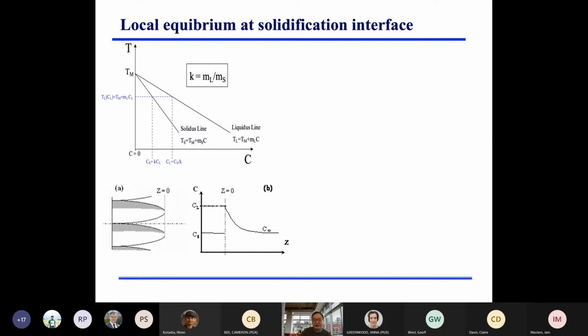So we use this solute blocking approach, and look at the equilibrium condition at the solidification interface. This is a schematic diagram of a binary phase diagram for an element with partition coefficient less than 1. This applies to aluminum copper, nickel aluminum, iron carbon systems, right? Now you have this liquid line, and this solid line. You cool down from liquid to solid, and how can we control the morphology of the solidified structures, right?